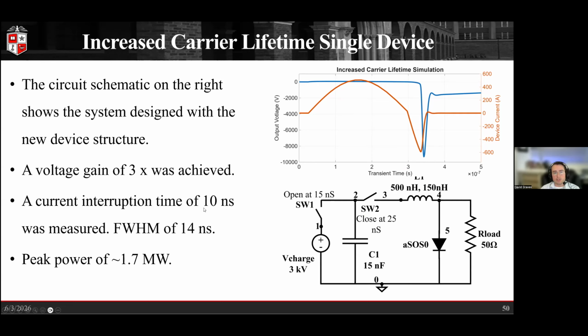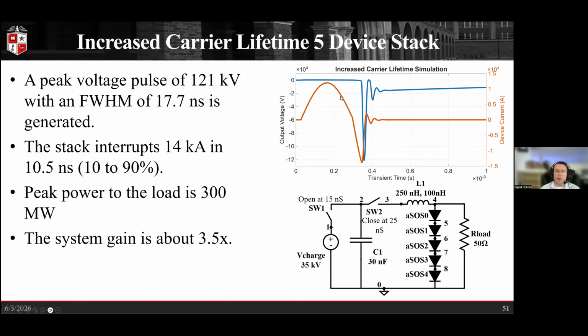The big difference, though, is now we have much wider full width half max, much higher energy delivered to the load. So we have a full width half max in this system of 14 nanoseconds. By contrast, we were looking at single nanoseconds with the lower lifetime. Peak power, fairly similar at 1.7 megawatts. And then when we're looking at stacking these devices again, we can do some more optimization.